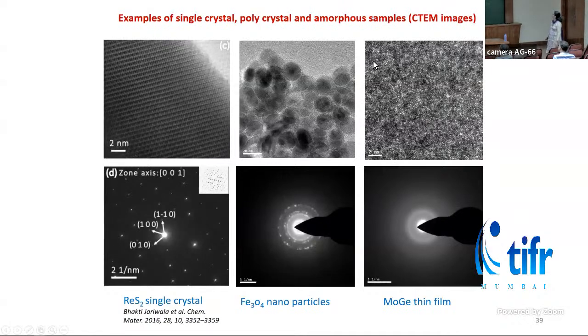Here are some examples of samples imaged using this TEM. So this is the diffraction pattern of a rhenium sulfide single crystal. By indexing and analyzing this diffraction pattern, we can identify the crystal structure of the sample. This is the lattice image of the sample, a high resolution TEM image, which is formed by the interference pattern of the diffracted beam and direct beam, and we can find the d-spacings in these